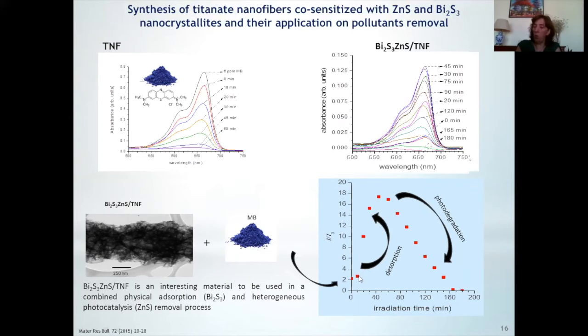Of course, we have the degradation of the dye, but at the same time, we have adsorption of the dye that is on the surface of the nanocomposite. And of course, during this period, the adsorption is higher than the amount of dye that has been degraded. Okay, after we start to have more degradation, we probably don't have more dye to be absorbed, and we will have the degradation of the dye.